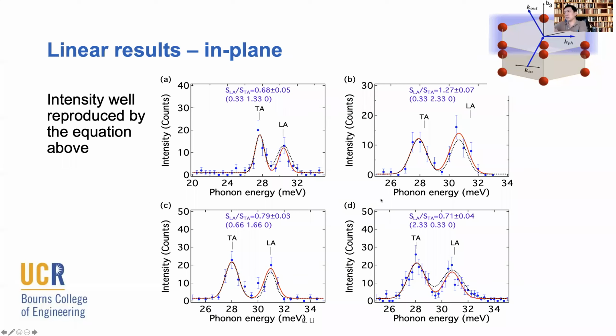So the take-home message is, if we do scattering along the basal plane, the theory predicts everything pretty well. We can tell the relative intensity between these TA and LA phonon modes. One of them will be left-hand circular polarized, and the other will be right-hand circular polarized. We can predict their intensity really well. That's not exciting. So when we came home with this data, we thought, oh, maybe we're just not seeing anything.